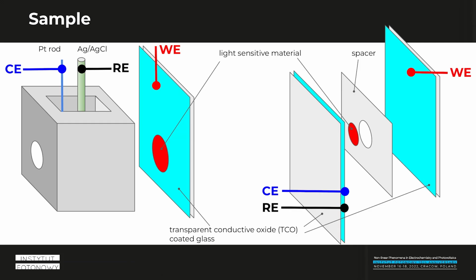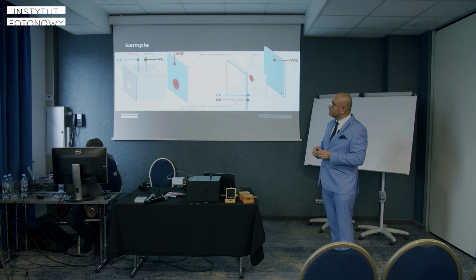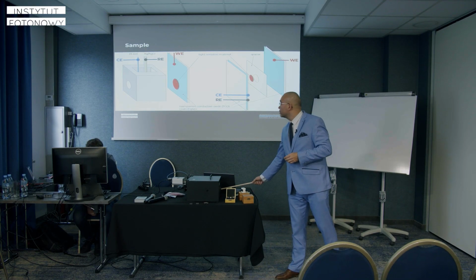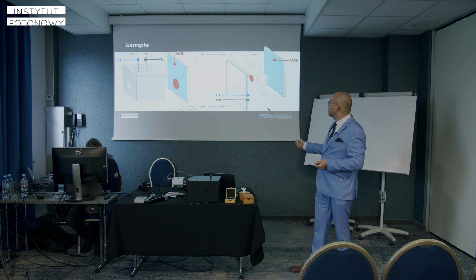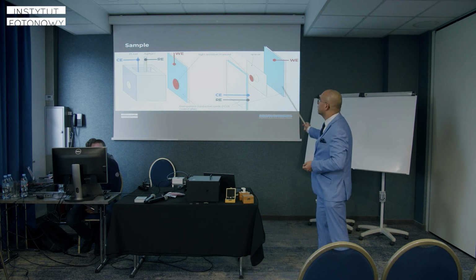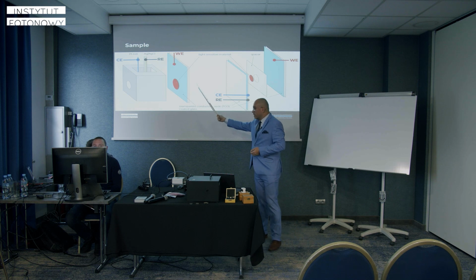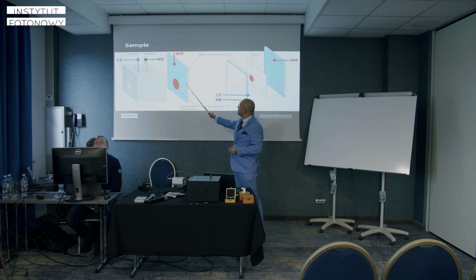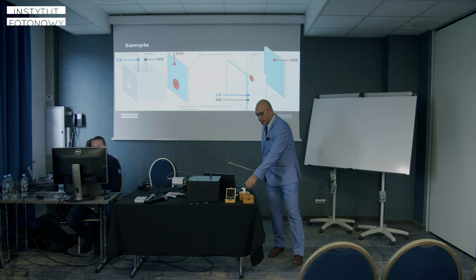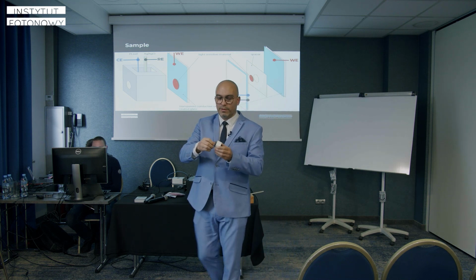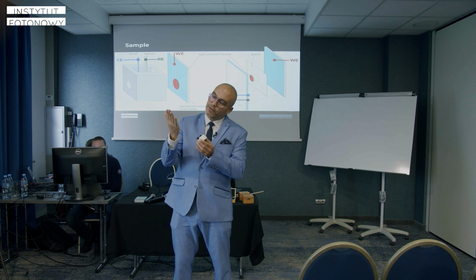How to mount a sample? There are several approaches. The easiest way in sample preparation is if you have a TCO, so an ITO or FTO substrate, a conductive layer covered glass substrate, and we just deposit some sample on your substrate from a solution or whatever you want. Instead of this plate, we put the sample facing the inside. We screw it up.